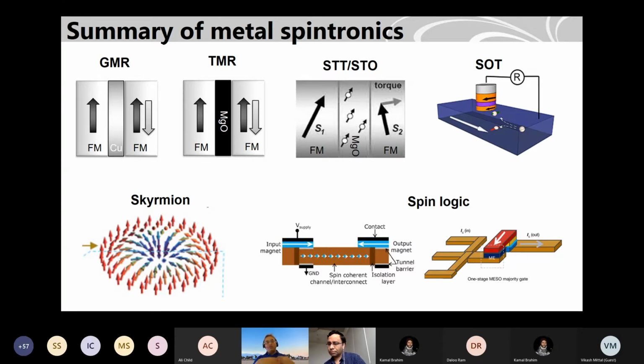For example, in high spin orbit material, the momentum and spin scattering are very much related. For example, in platinum, once an electron scatters, it means spin is also scattered. Also same as with a topological insulator. So they are very highly coupled. So it's like spin momentum locking. In that case, spin relaxation and momentum relaxation are the same. But in case of graphene and aluminum, graphene case I'll show you next week. So spin relaxation time is much higher, in nanoseconds, for graphene and aluminum.